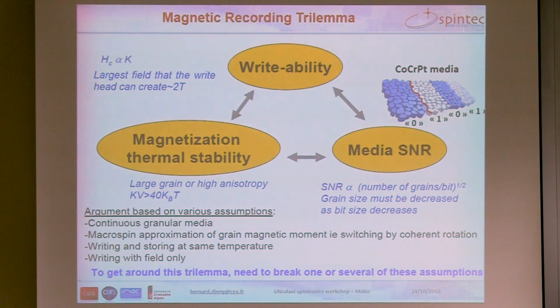So if we want to maintain a sufficient signal-to-noise ratio in the media when we decrease the size of the grain, we have to keep the number of grains per bit constant, of the order of 10 grains per bit nowadays. But we need to reduce the volume of the grain to actually reduce the size of the bits. So this means that to keep a sufficient signal-to-noise ratio, we need to keep approximately 10 grains per bit. So if we want to shrink the size of the bit, we need to shrink the size of each grain.